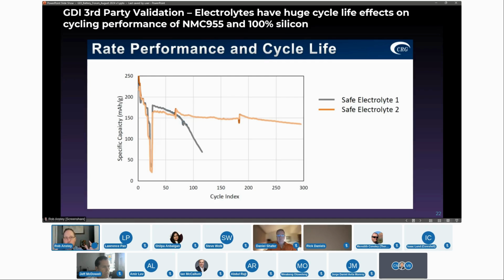So once again, electrolytes do have a huge part to play in cycle life. And some customers are going to have to pay more for electrolyte to get better cycle life unless your application doesn't need it. And you have to get the formulation right. So electrolyte 1 had a much higher resistance. It was much more viscous. And as you can see, that actually only got about 100 cycles because you start to have a buildup in cell resistance. So you can't put in any electrolyte. You have to put in something that is tuned to your anode.